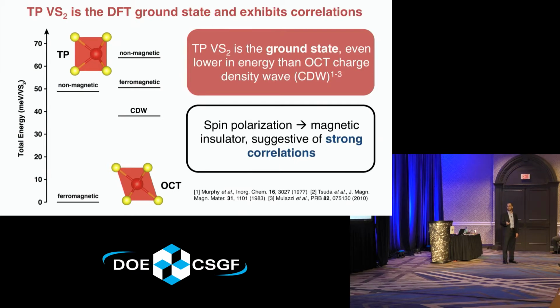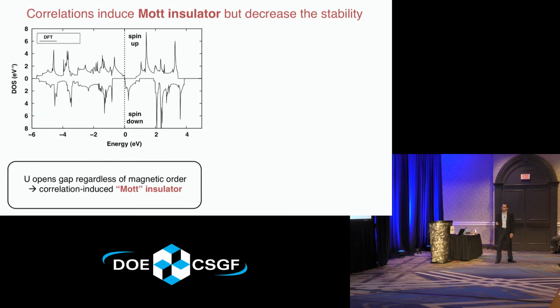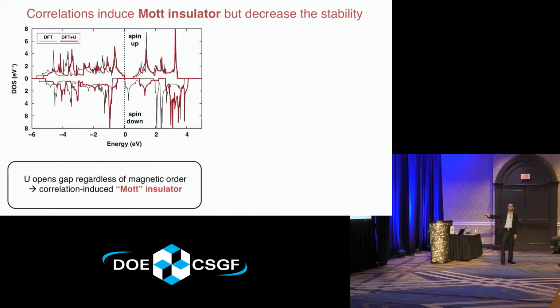Now we can explicitly explore the role of electronic correlation by going beyond density functional theory, using that DFT plus U approach, in which we solve our DMFT equations with an approximate solution. So this is the electronic spectrum of that magnetic state. You can see basically our isolated band is just spin split. So this is just within DFT, or U equals 0 essentially. If one then adds on that explicit Coulomb interaction, you can see the main effect is that it makes it increasingly insulating.